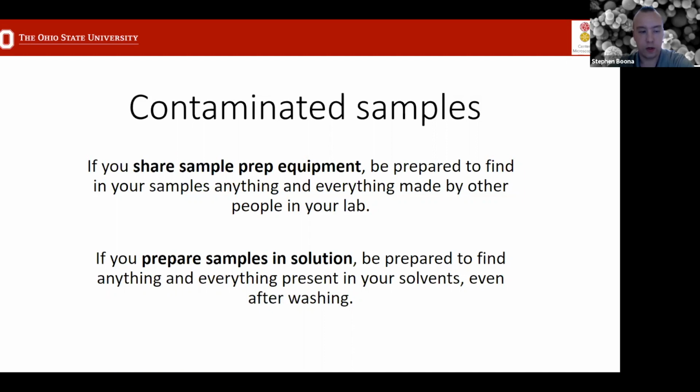Similarly, if you work on materials that you prepare in solution, so you work with buffers or solvents, it's not necessarily uncommon to see leftover salts or other things that are present after the material has been dried. Okay, so we talked a lot about how X-rays can come from lots of other places besides your sample, but in these cases, they would be real signals actually coming from the sample itself, but not where they're supposed to be in terms of the sample composition. So sometimes it's a real signal and you have to be aware of that possibility.